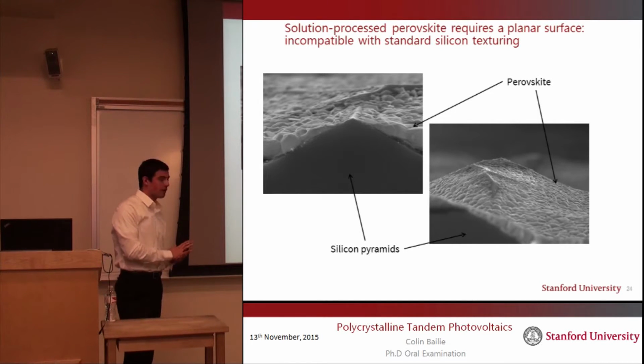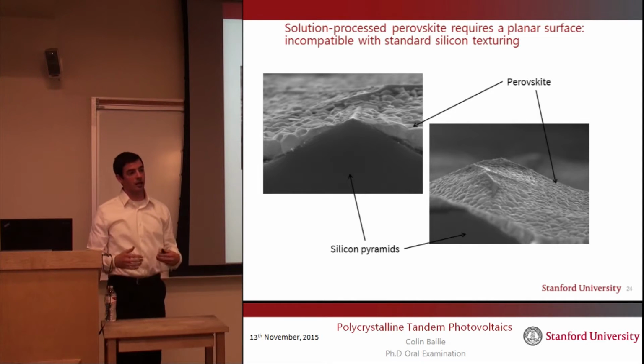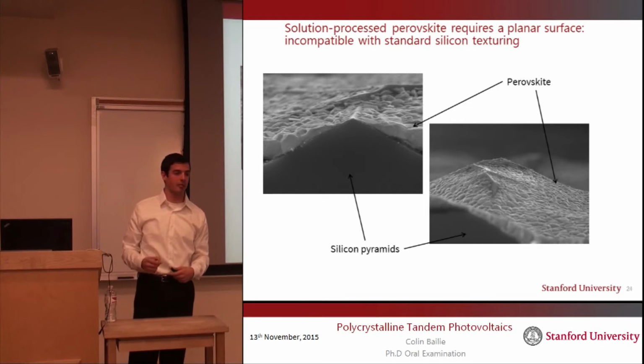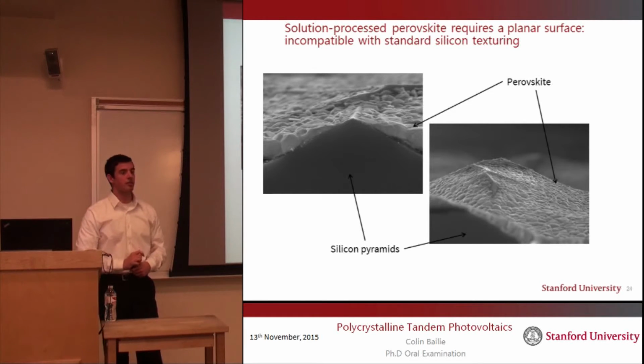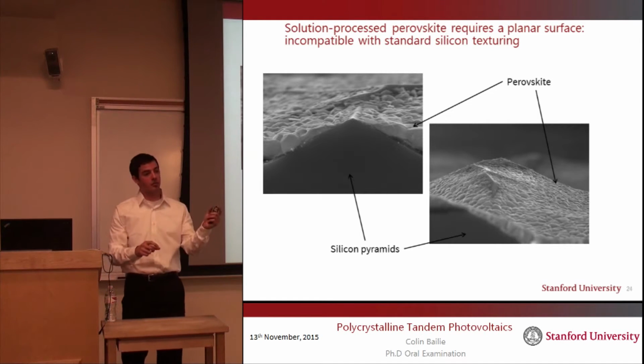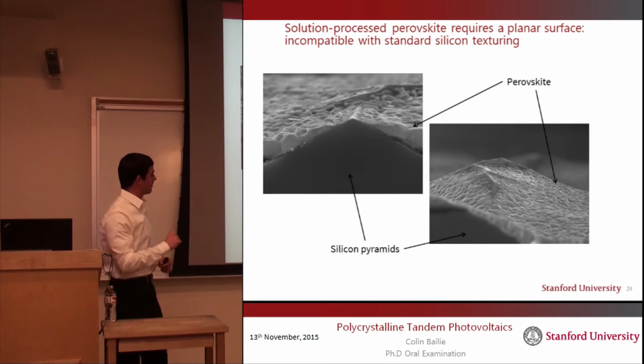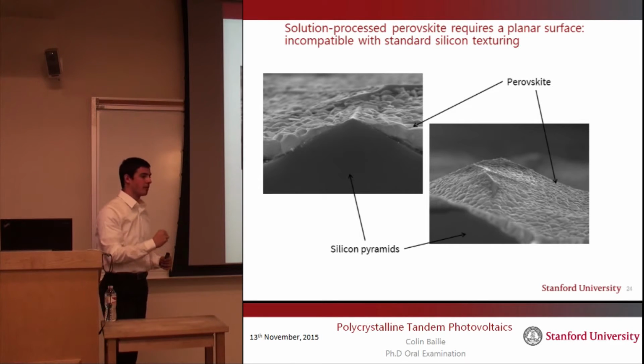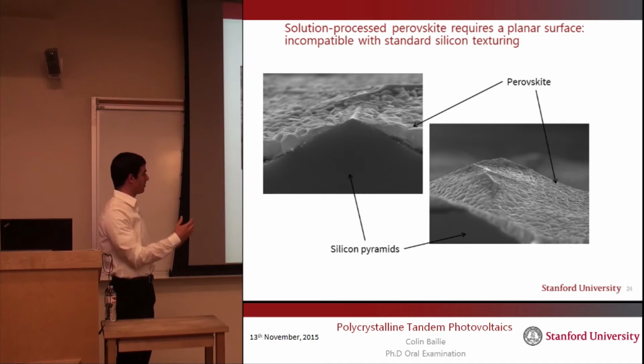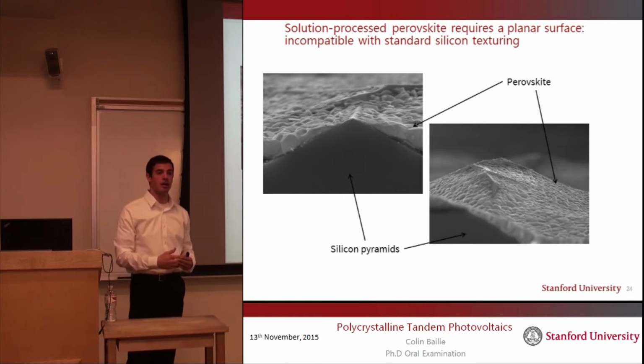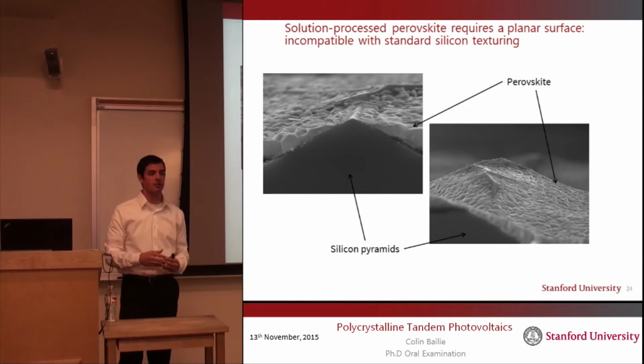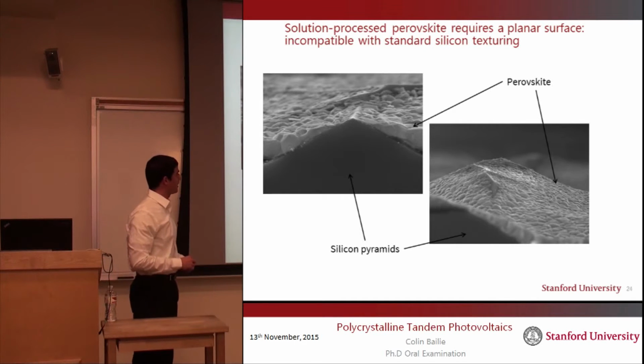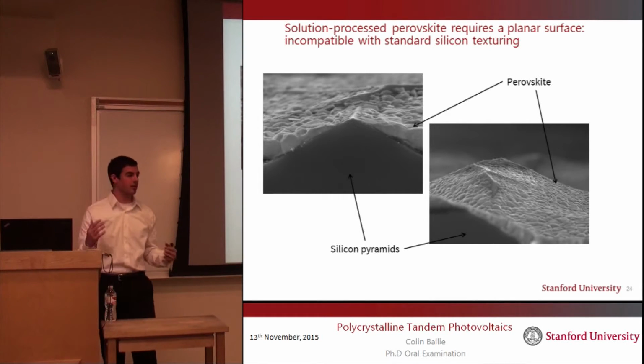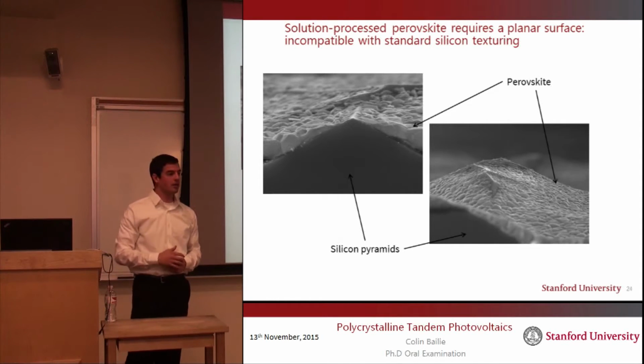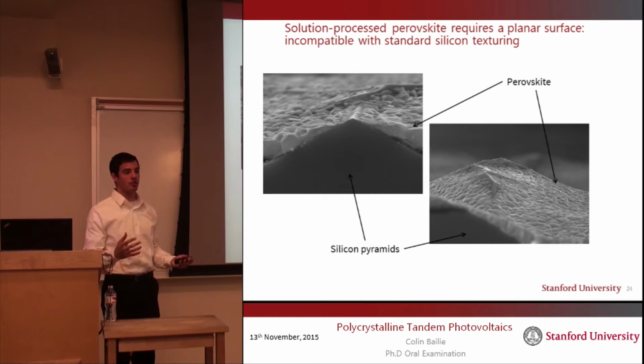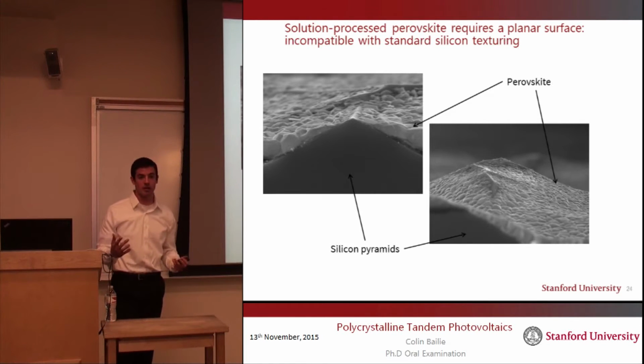On the other hand, the perovskite is deposited by solution processing, and solution processing is an inherently planarizing type of deposition, meaning that within these pyramids you will get more perovskite in the troughs and less perovskite on the peaks. And sometimes this is okay, but because we're only trying to deposit half a micron of perovskite and instead we're depositing it on 5 to 10 microns thick of this roughness of the silicon pyramids, the consequence is that on the peaks there is no perovskite at all. And when there's no perovskite at all, then when you finish your device and put the metal on top, you have metal directly touching your silicon, and that's a short, and your perovskite will not be operating in the way that you want.